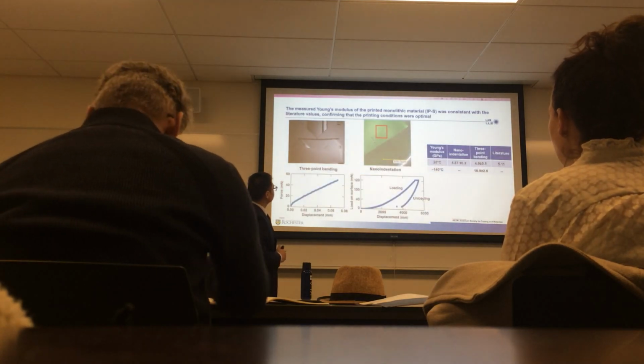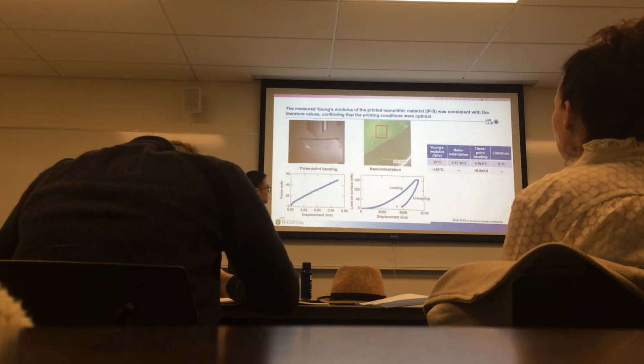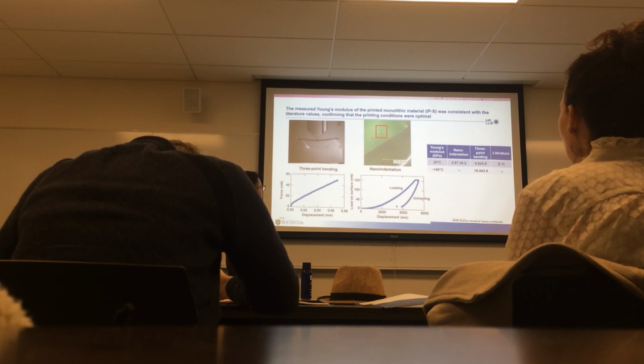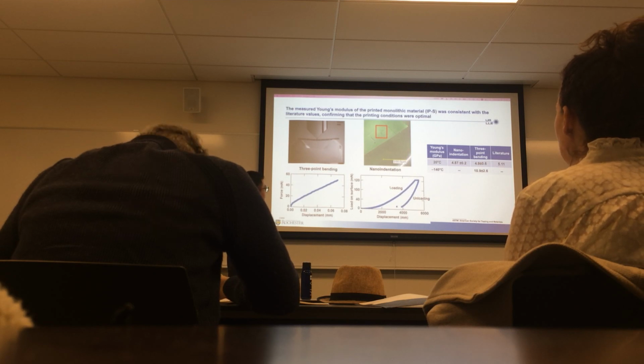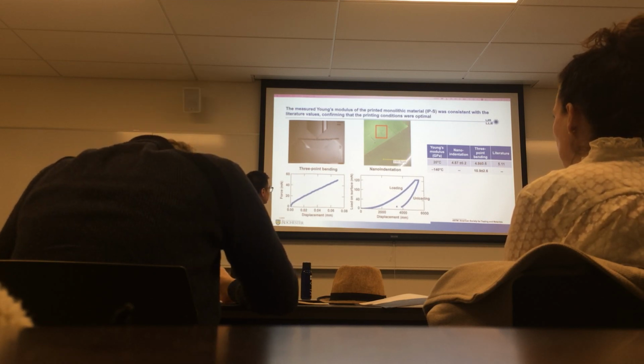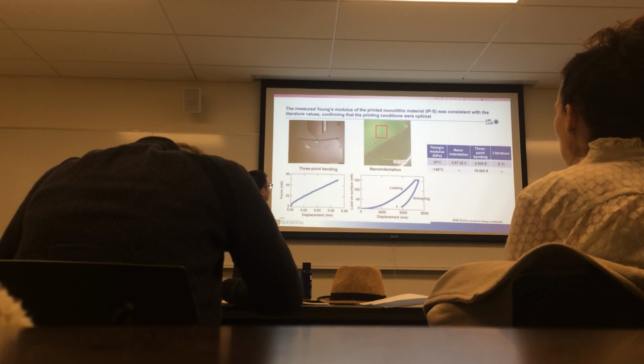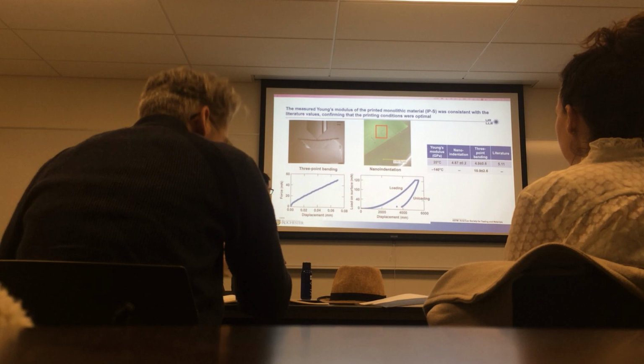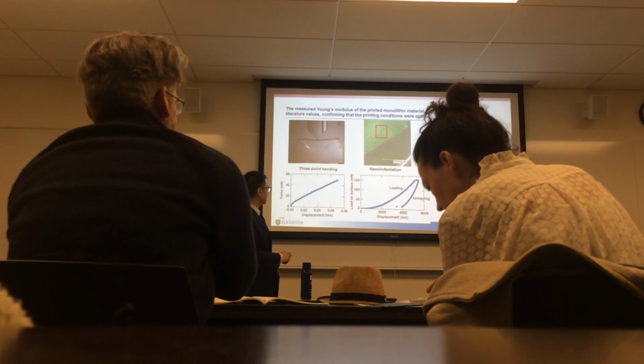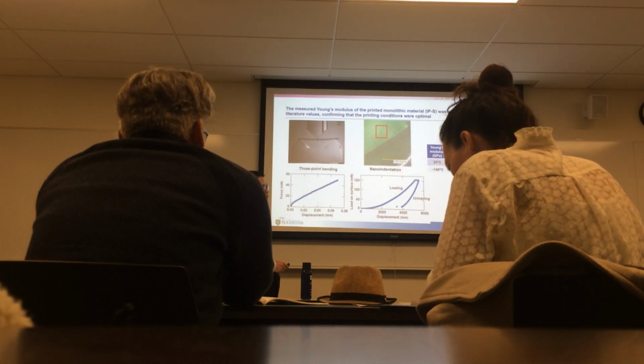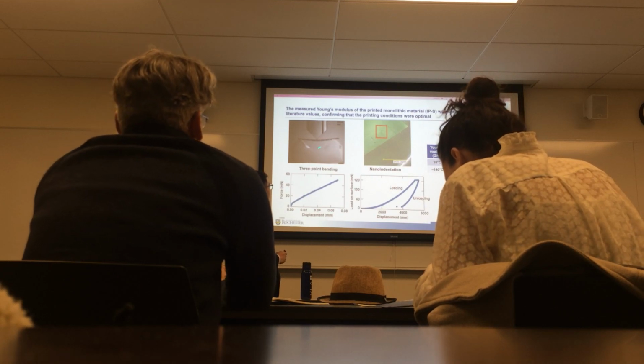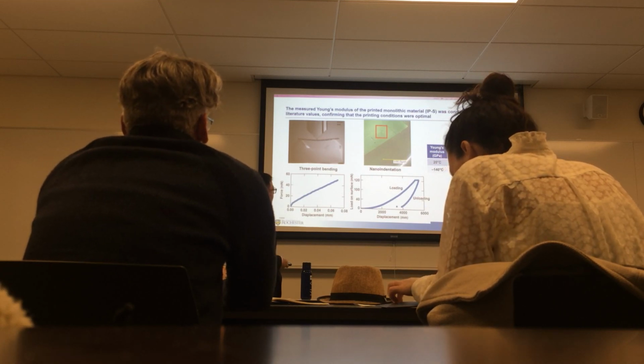There are two ways to measure the material properties. The first method is called three-point bending, and the second one is called nano-indentation. For three-point bending, we place our solid beams on the supports, and in the center a probe compresses. The equipment records the force and displacement curve, and from this curve we can calculate the Young's modulus of these materials.